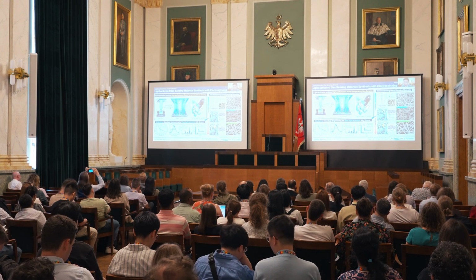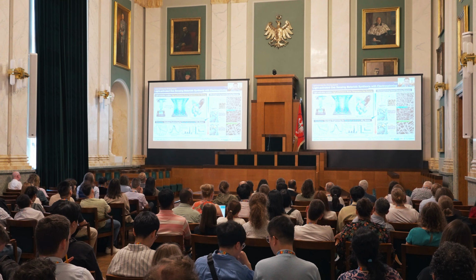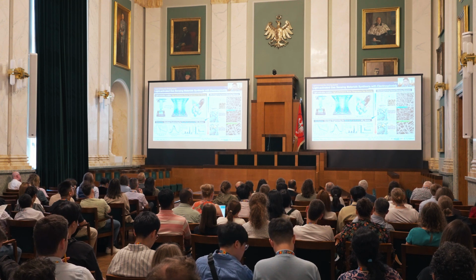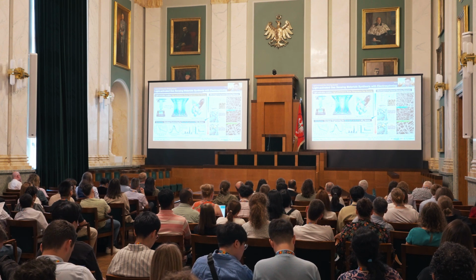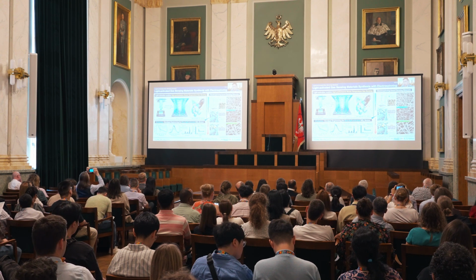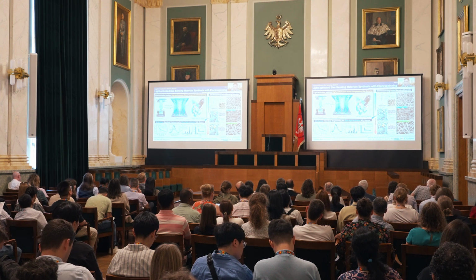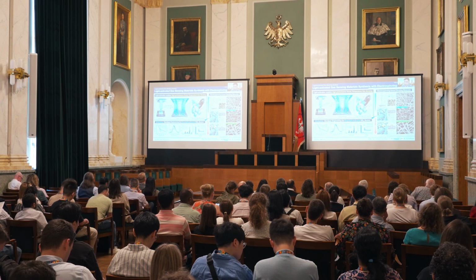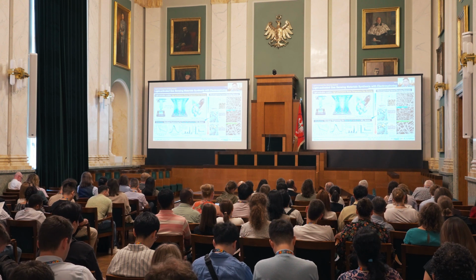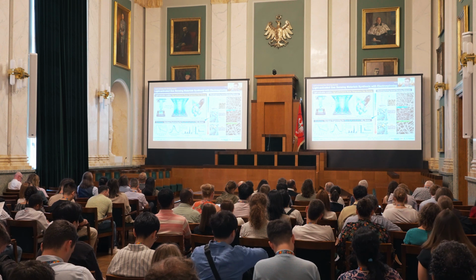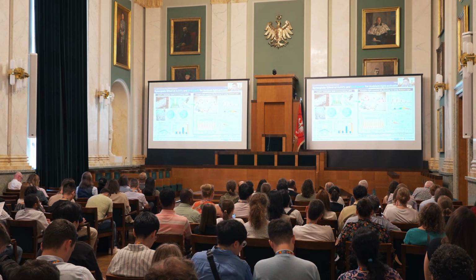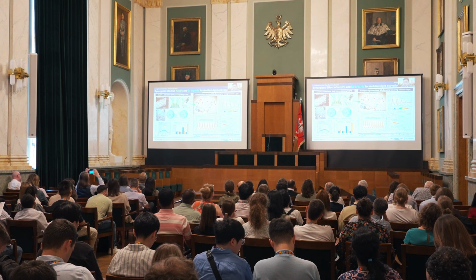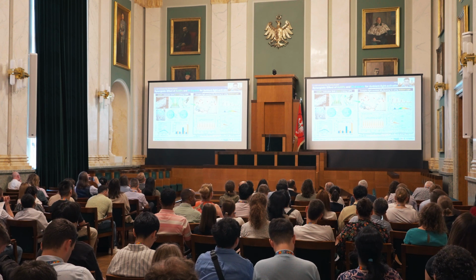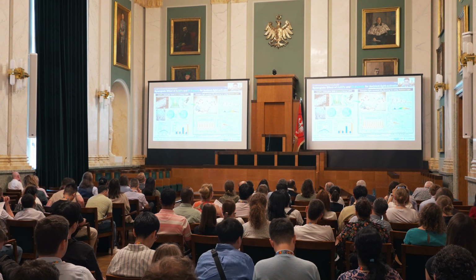Additionally, we're working on light-activated room temperature gas sensors. For example, this is indium oxide, okay? The band gap is about 3.0 electron volts. By simply doping bismuth within this indium oxide lattice, we can reduce the band gap. That means blue light activation is possible. But green light activation is not enough, so that's why we additionally decorate gold particles for the surface plasmonic effect. In this case, the green light activation is hugely increased.